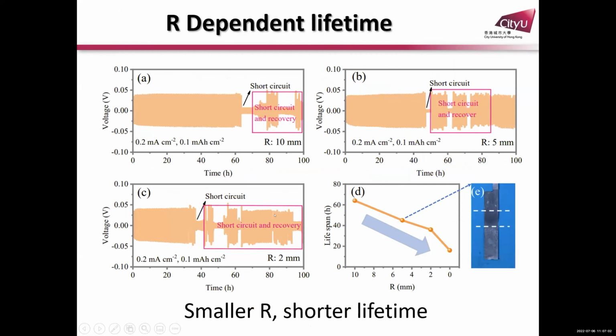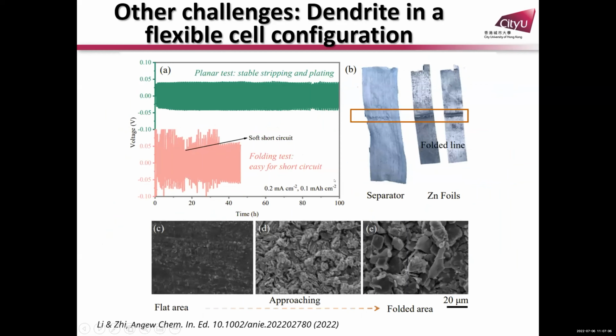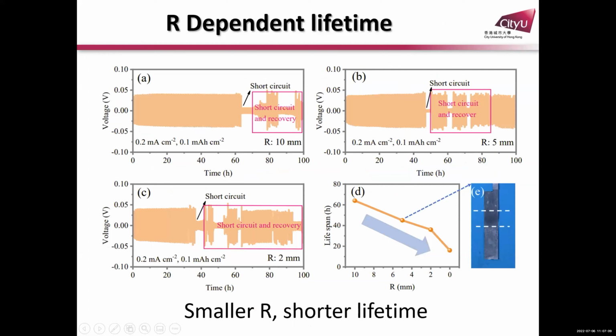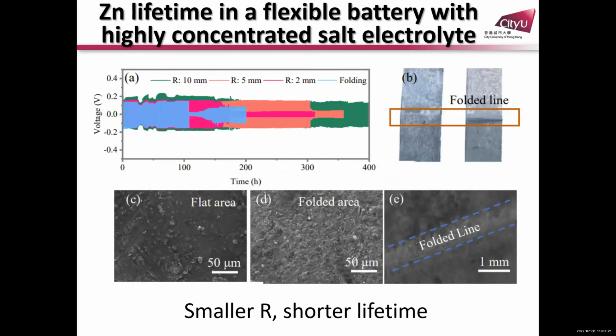We tried to investigate different diameters. If you fold it with different diameters, we definitely see longer cycling time for a large diameter, and shorter cycling time for a small diameter. We're trying to solve this problem with a water-in-salt electrolyte. It was reported previously that water-in-salt electrolyte can prevent the growth of the dendrites. But even if you use water-in-salt electrolyte, we still notice the problem of R dependence. For example, if you fold it, you still have a very short lifetime. But if you use a very large R value, you have longer cycling stability. So that means even with a highly concentrated salt electrolyte, you cannot solve the problem.